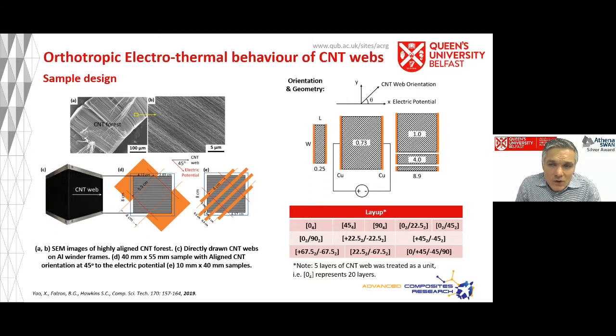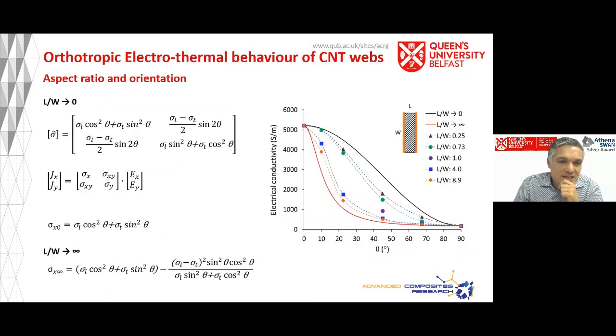And what we have done is then to look at laying up. We made a number of samples, so we made two types of samples. One with a low aspect ratio, as you can see here, and the reason why I've drawn it this way is that if I wanted, say, my nanotubes to be at 45 degrees, well, I've cut at 45 degrees, and then I've got my electrodes on either side, and you can see that the aspect ratio there is pretty low. But I can also make much longer specimens so that I can look at the influence of the aspect ratio on conductivity, because it does make a difference.